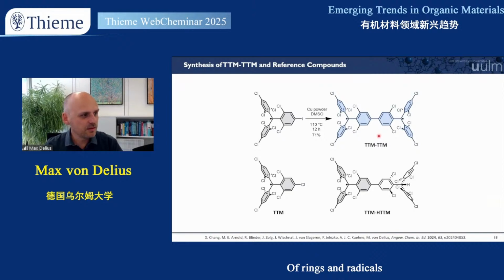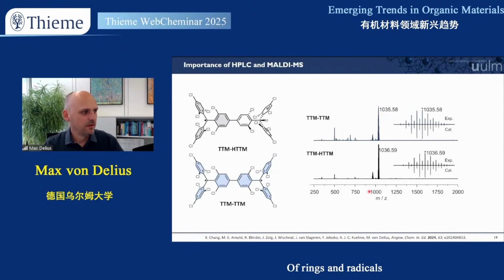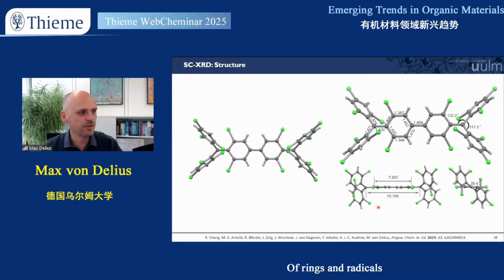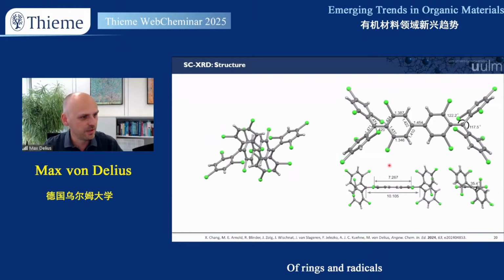So Xingmao made these three compounds, optimized the synthesis, 70% yield of this new trityl diradical and the monoradical for reference here as well. So purity, as I said before, is very important. We did also ascertain this as much as we could, as we later found that light can actually lead to some degradation. We ascertain the purity of these radicals, which is important because NMR is not really your friend here.